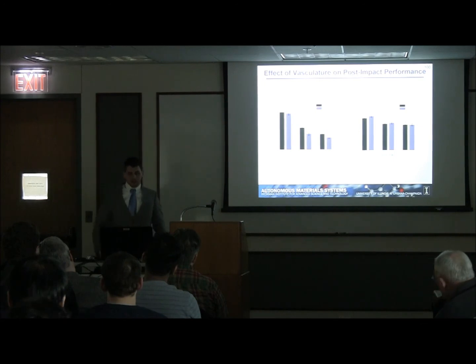Is that a fatigue issue at all, or having that capillary almost act as a little starter crack in there under fatigue? It could act as a starter crack, but it could also act as a way to arrest the fatigue crack. There was work previously in our group where Andrew Hamilton, someone from our group before, looked at how the microchannels actually increase the number of cycles to failure in fatigue by arresting a fatigue crack.